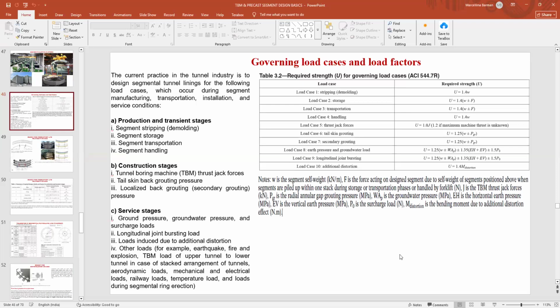It is not uniform because, as I told you, when we were crossing the Haidarnala part in Lucknow Metro, that part we made a very special segment. Here we did not increase the thickness of the segment, but we made all the reinforcement epoxy coated, because the Haidar canal is basically a sewage canal. So here I will have a very aggressive ground for durability, while other parts will have a very light or moderate type of exposure.